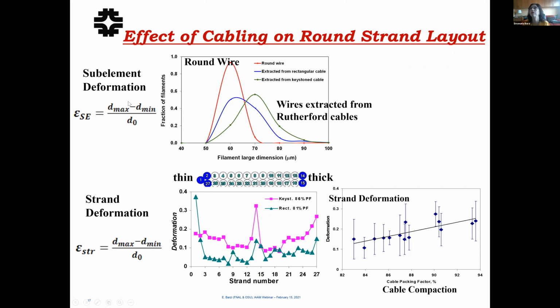So let's check how much the subelement deforms in these wires. You can come up with a definition of deformation. This was the definition that we used, but it's not written in any textbook. You can choose your own criteria. So this was a definition of subelement deformation. And for instance, on the x-axis there is the dimension of the filaments, and the y-axis is the fraction of filaments that had such dimension. You can see, for instance, the round wire has its own filament distribution. So nominally, let's say the filaments have to be 50 micron in diameter, but of course you are going to find a distribution of their sizes because they come out of extrusion and drawing. But when you look at the extracted wires, as you can see, the average size of the filament goes to the right, it increases, it flattens, it deforms, and the standard deviation, of course, increases. So this is an example.